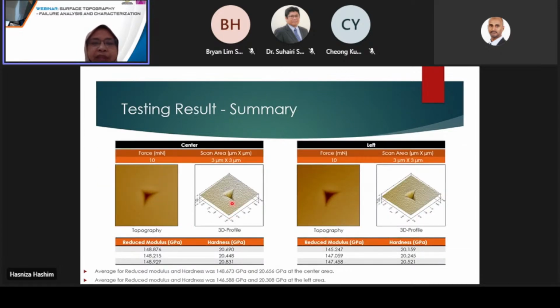Before we do the indentation, we have already done the scanning on the area to be indented. From this in situ image, we can see that it is very fine and smooth, and this meets the requirement for nanoindentation. Once we do the nanoindentation, we can capture the image using the in situ imaging, where we can see the topography of the indentation and also the 3D profile. And it comes out with the result of modulus and hardness. From these samples, we can see that both the center and left area of the wafers produce almost the same result.